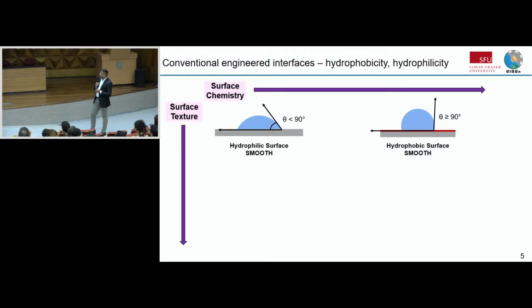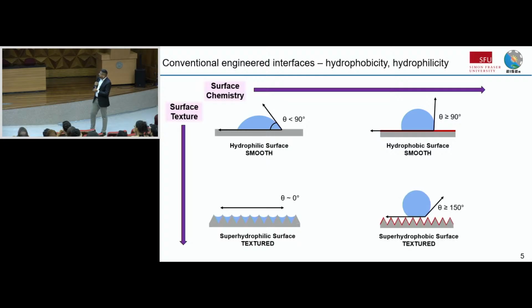But now this is where texture comes in. Remember the hills and valleys that I said? So if you take that smooth material and now add these hills and valleys, or microtexture it, then the contact angle becomes 0. That means you can get extra wettability. And then the same thing with hydrophobicity. If you make it textured, you make it extra hydrophobic, right?